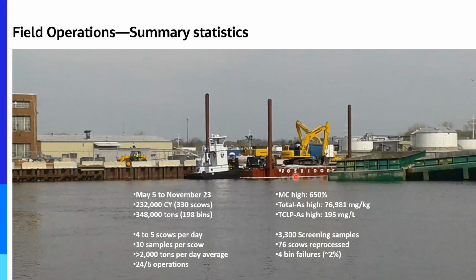So in summary, we worked from basically 6 months, spring to just before US Thanksgiving, 232,000 cubic yards or 330 scows. That corresponded to 348,000 tons or 198 bins, right? That had full TCLP compliance on them. So 4 to 5 scows every day, 10 samples per scow, greater than 2,000 tons per day average processing, 24/6 operations. The highest moisture content was 650. The highest total arsenic, right, was almost 77,000. This is comparable to an arsenic ore.